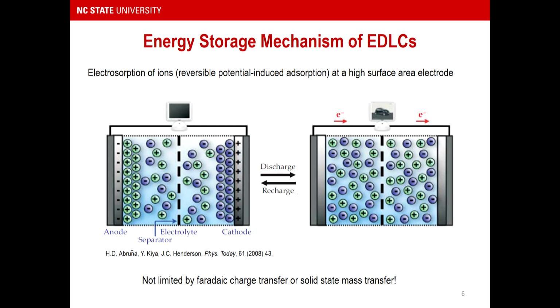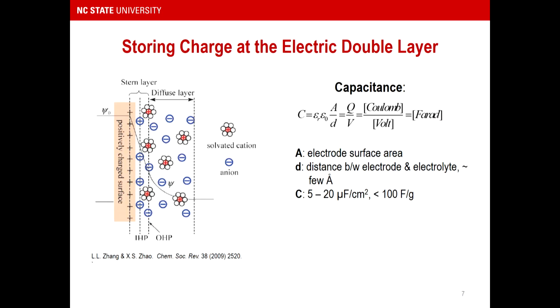So the diagram for this paper comes from Tito's very nice work in Physics Today, where we see that during the charging process, you have the formation of double layers at each of the electrodes, the positive and negative electrodes, and during the discharge processes, these ions simply desorb from the surfaces and then can be used to power some devices. There's no Faradaic charge transfer reactions that take place, and there's no solid-state mass transfer, which is why the commercial devices can reach those extremely high power capabilities.